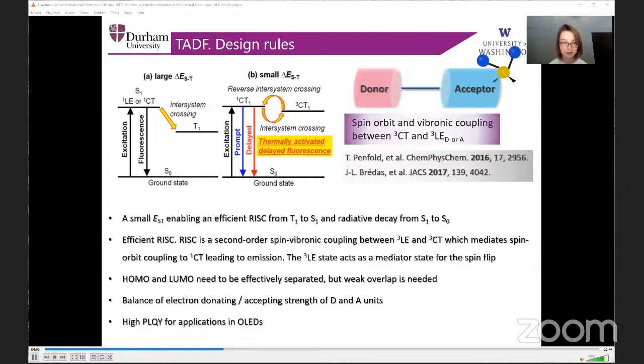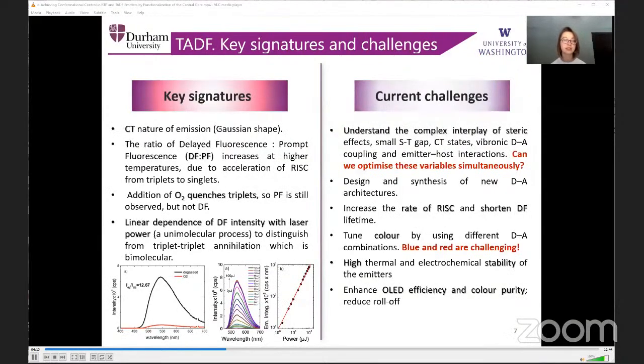to enable an efficient RISC from the triplet to the singlet state and a high fluorescence quantum yield. Key signatures of the TADF process include the charge transfer nature of emission, the ratio of the late fluorescence to prompt fluorescence increasing at higher temperatures, the addition of oxygen tending to quench triplets, and most importantly, we are looking for the linear dependence of the late emission on laser power to distinguish it from the triplet-triplet annihilation process. Current challenges include understanding the complex interplay of steric effects, small singlet-triplet energy gap, charge transfer state, vibronic coupling, then also looking for and designing new structures, enhancing the OLED efficiency and color purity, and trying to increase the rate of reverse intersystem crossing.